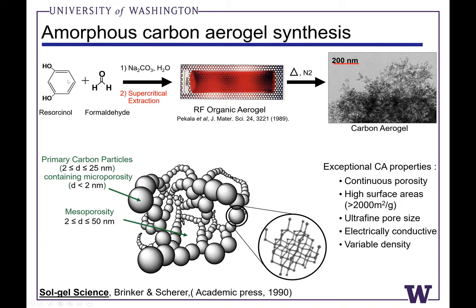And this is a resorcinol formaldehyde mixture that's typically a polymerization reaction, either acid catalyzed or base catalyzed. We can work in water for base catalyzed reactions. We typically work in acetonitrile for acid catalyzed reactions, but this is just a cross-coupling reaction, a condensation reaction, where effectively we're making carbon-carbon bonds, oxygen-carbon bonds, and what we get is a gel. This is a really high surface area organic aerogel, hydrocarbon aerogel.